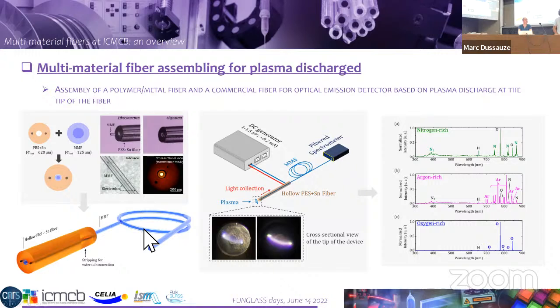But this is part of the challenge, actually. It's not such a complicated challenge, but we have to be at the good target. One thing we observed, for instance, is that the diameter of the electrode is important, because if the electrodes are too small, they are hard to connect, and then the resistance is really strong. So we have to have relatively large preforms with large metallic electrodes. And then the hole has to be at a good ratio, so that we target, we know that we want to be at 130 microns inside. So just knowing this information, we apply the drawing parameters.